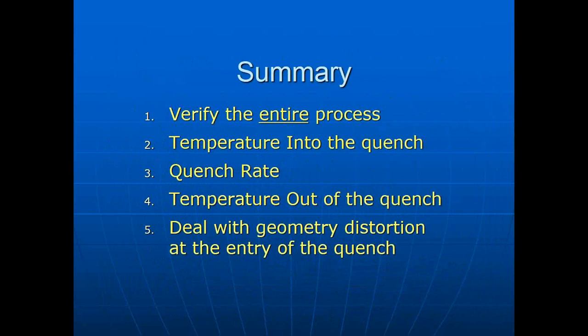So to summarize our discussion today, if we face issues with properties or geometry with a structural alloy, we want to verify the entire process. Do not assume it is a quench problem. We need to make certain the entire process is in control. We need to verify that the temperature into the quench is high enough. We need to evaluate the quench rate. We need to make certain that the temperature out of the quench is low enough. And we need to deal with any issues of geometry distortion at the entry to the quench.